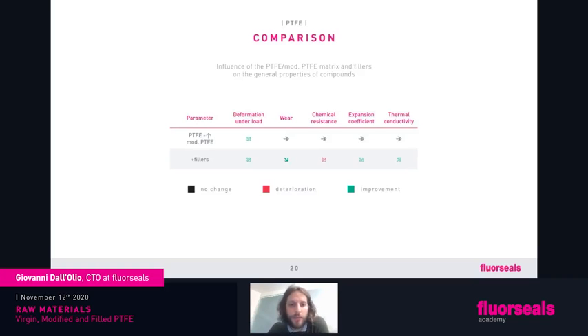Again, briefly, on the first row, we can see the difference between PTFE and modified PTFE. Mainly, we keep all the properties constant. The deformation under load is reduced. It's a green arrow, so that's a good thing. And when we add the filler, generally speaking, we improve the deformation under load. We improve the wear behavior a lot. We do reduce the chemical resistance, and that's not good, or at least it's not always good.